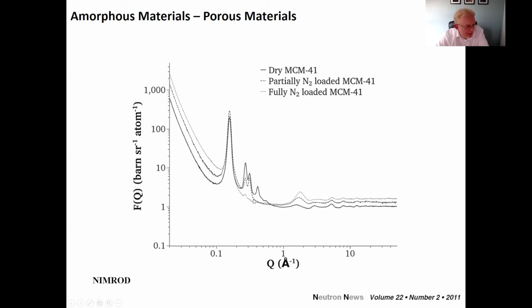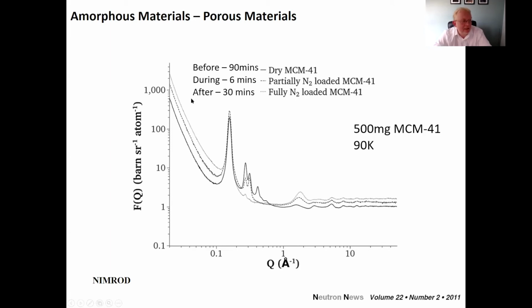You start to see the appearance of these peaks at different energies. And then finally, we have the fully loaded material, which is the top line here, when it's fully loaded with nitrogen. Now, this was a dynamic experiment. It was done on 0.5 gram of material at 90 Kelvin. The before data took 90 minutes to collect. During nitrogen loading, data sets were collected every 6 minutes, and then the final data set was 30 minutes.